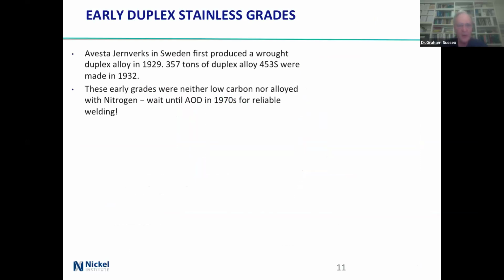So just a bit of history. Sweden back in 1929. 357 tons of an alloy made in 1932, so a long time ago. And the early grades were neither low carbon nor alloyed with nitrogen. You had to wait until the 1970s when we got argon oxygen decarburization and control of gases to get reliable welding and to get good compositions.